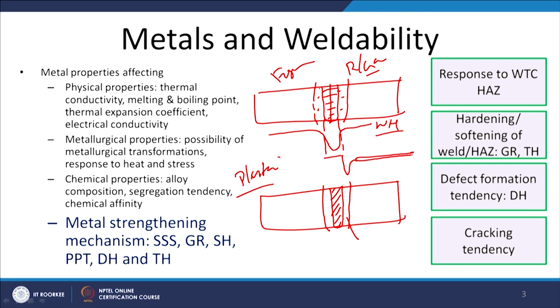So the base metal is harder and stronger, but the heat affected zone will be softer, and this is attributed to the loss of work hardening effect, annihilation, and the reduction in the number of dislocations due to the heat being generated in case of the deformation based approach. So a similar trend we may find on the opposite side like this. So softening is primarily occurring in the heat affected zone, and hardening is taking place in the weld zone, where controlled plastic deformation has been used.